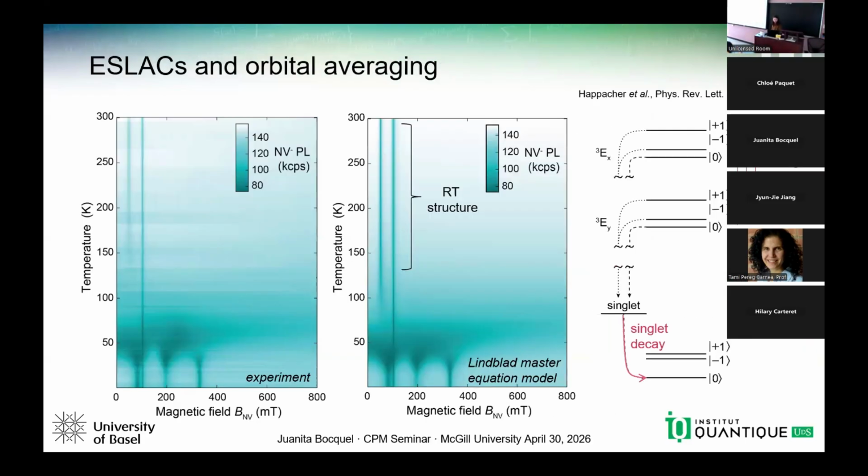And we also developed a quantitative model based on the full low temperature Hamiltonian for this particular defect, taking into account parameters that we extracted from experiments at low temperatures. We also included rates that are temperature dependent, everything that has to do with phonons. And we used mainly modeling this rate, but also more importantly, this rate, which is a phonon relaxation related rate that basically mixes the two orbitals. So you have this increasingly fast spin conserving transition that occurs between the orbitals. And this increases as the temperature goes up.